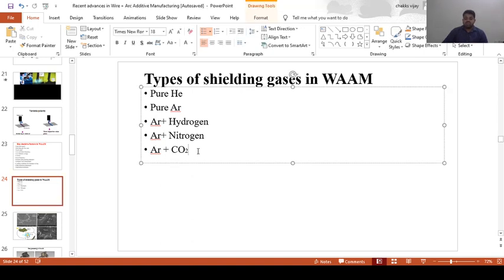Okay, you can even go for CO2, but not for the TIG process, because the thoriated tungsten rod has a very high thermionic emission. CO2 is a metal active gas, which will react with the tungsten and start leaching out the tungsten rod, causing tungsten inclusions in your workpiece. The TIG rod life will be very short if we use an argon CO2 mixture, so it is generally not recommended. For normal MIG or MAG welding we generally go for it, but for TIG welding we never use argon CO2. Other than that, we can go for argon nitrogen or argon hydrogen for TIG, but not CO2. Argon CO2 we never use for plasma and also for pure TIG.